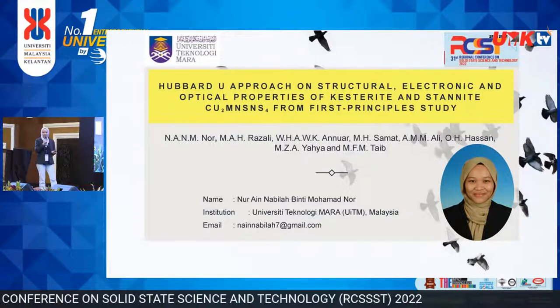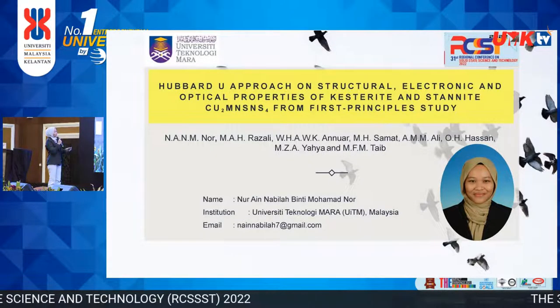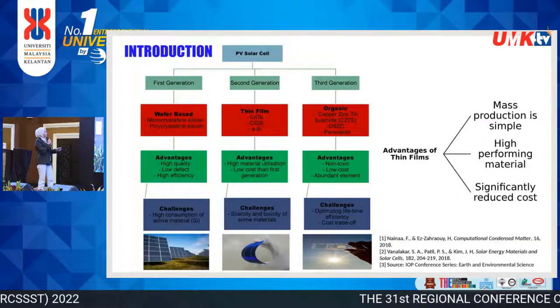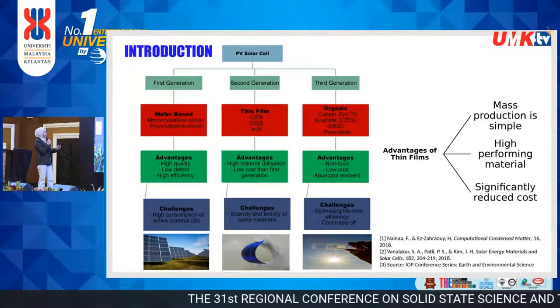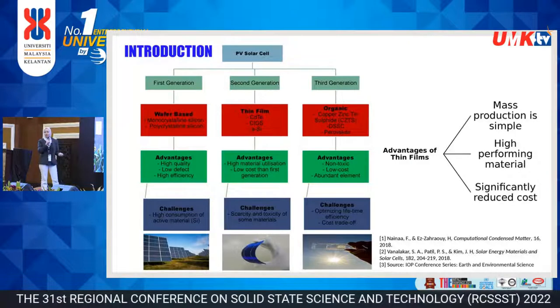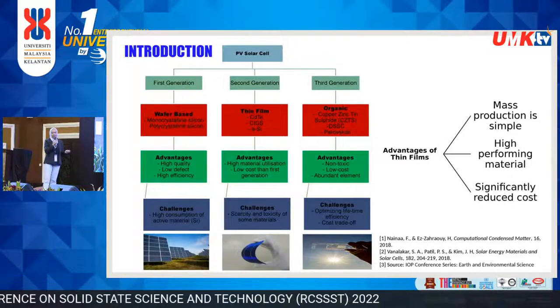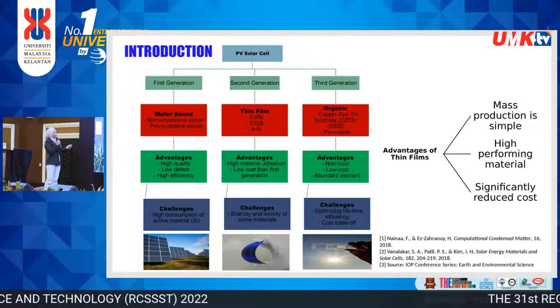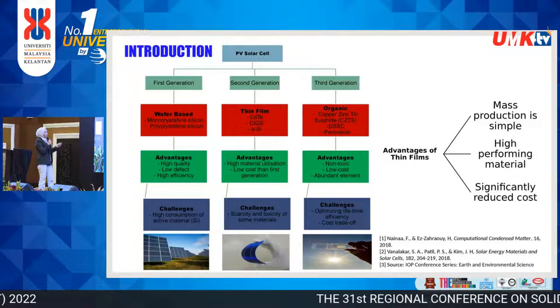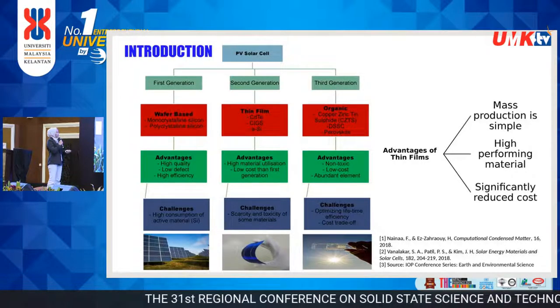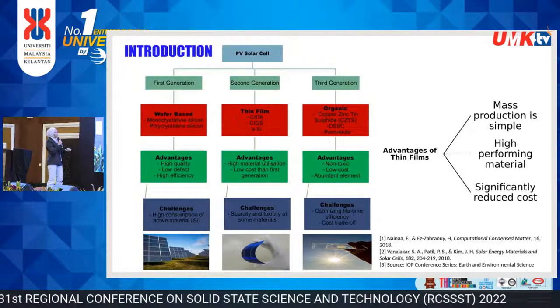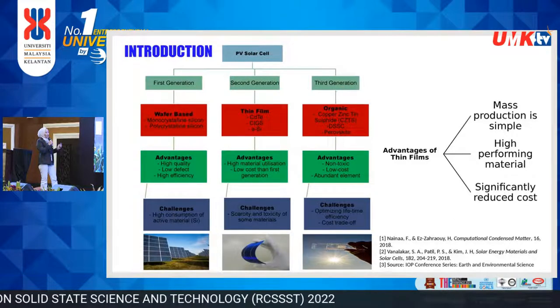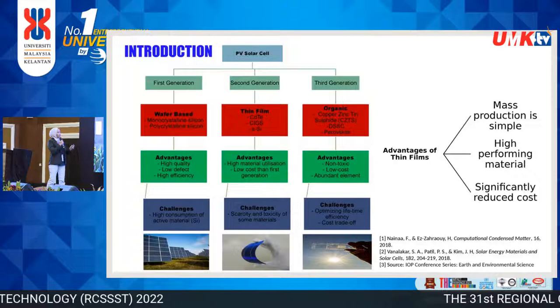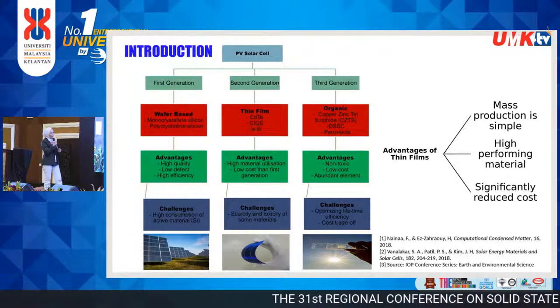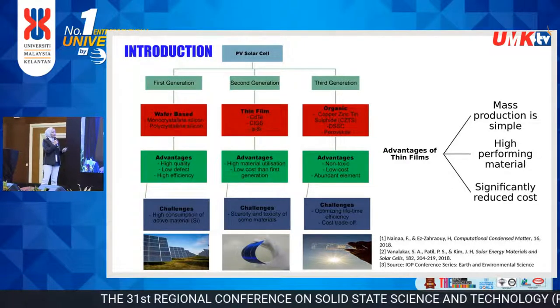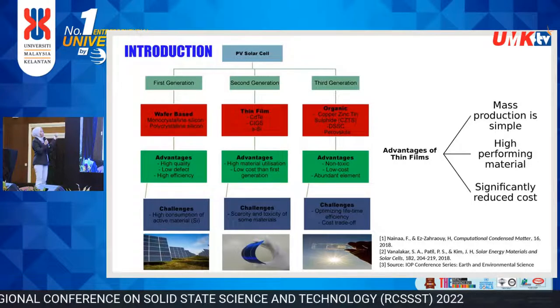As we know, for PV solar cells there are many types of solar cell, the first generation being from the wafer base. The commercialized one is the crystalline silicon with the advantages of high quality and high efficiency. And then the second generation is from the thin film, as we know, the cadmium telluride and the copper indium gallium selenide, with the advantage of lower cost than the first generation. And the third generation comes from materials like copper zinc tin sulfide, the CZTS. Among these three, I will focus on the third generation, which comes from the copper zinc tin sulfide. So the advantages of the thin film is that mass production is simple and the cost is significantly reduced compared to the first generation.